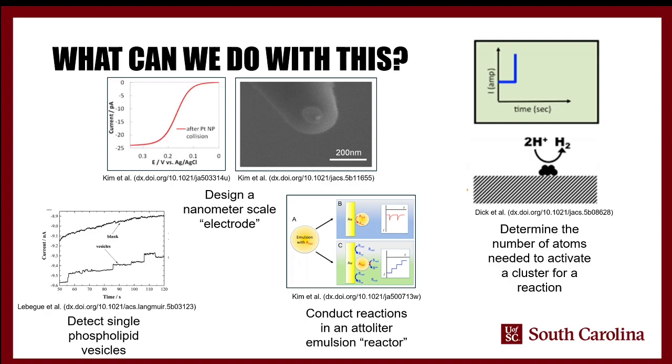Traditionally, to do this, you have to take a metal wire, start out with one that's already very small, heat it with a laser, and then pull it very, very quickly while it's in a glass sheath, and hope that you pull it in such a way that it both stretches out and becomes very thin, but also that it doesn't break the glass sheath that surrounds it, or that the wire itself doesn't break before you've reached a satisfactory diameter. And even with all of that, you're lucky if you get a nanometer scale diameter. You're lucky if you get a diameter that's maybe 50 nanometers.